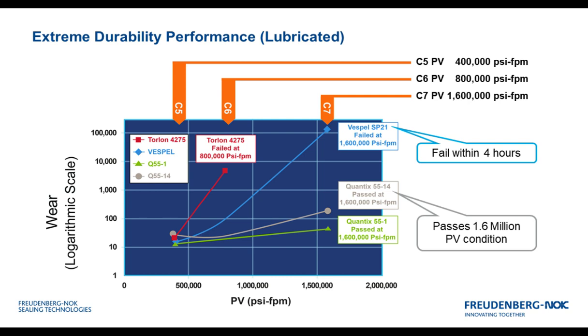Taking the information we just had, the same materials we just looked at, which were tested at this condition C5, which happens to be a PSI times feet per minute PV value of 400,000, you can see that the materials have very little variation in wear. The wear is on a logarithmic scale, so there's huge changes in wear as you move up this graph. But when we move to condition C6, you can see now we went from 400,000 to 800,000 PSI times feet per minute. At that condition, we cannot pass the 4-hour test with the Torlon, where the other materials still continue to be used.